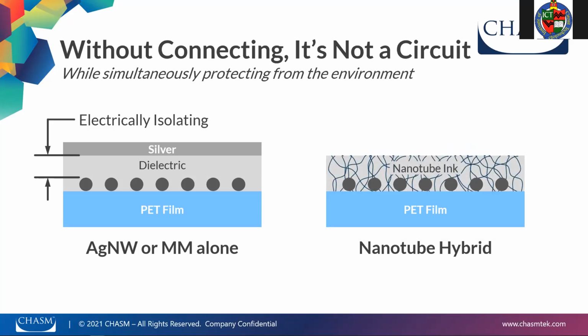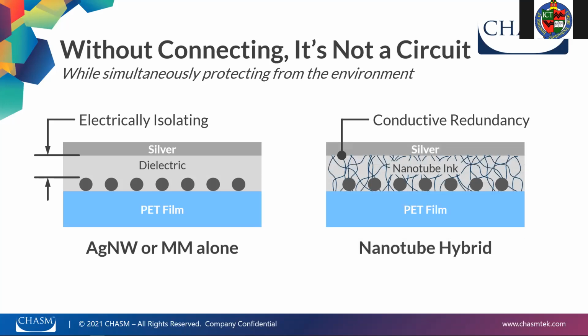In the case of the nanotube hybrid, nanotubes that are dispersed in the nanotube inks are not only conductive, but they're made of carbon. Carbon is environmentally stable and it's even protective in hot, wet conditions. So the conductive redundancy of the nanotubes extends not only up to the surface, making it simple and robust to make connections, but also the nanotubes themselves form networks around the metallic conductors, so that if the wires were to break or to separate, the circuit is still completed by the conductive nanotubes. So desired finished circuits can be made from nanotube hybrids that are much simpler, faster, and more cost-effective to fabricate, plus offer the enhanced environmental stability and durability in the circuit's lifespan.